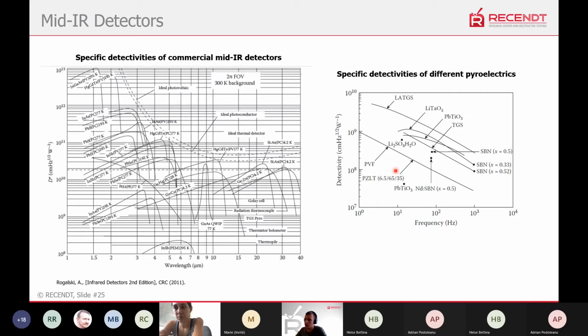Now I will very shortly tell about detection in mid-infrared. That was the main challenge, since we have sources, as I mentioned already. Here it's quite problematic, first of all, because there are no real array or linear array cameras in this range, and detectors are significantly less sensitive in the range of interest. If you are around 4 micron, what we would have is significantly lower detectivity. Detectivity is reciprocal to noise equivalent power. For example, an indium gallium arsenide detector at room temperature in the near infrared would have detectivity several orders of magnitude higher. For comparison, the detector I use now has detectivity of the order of 10 to the power of 10 at room temperature, and that's already quite good for this range.